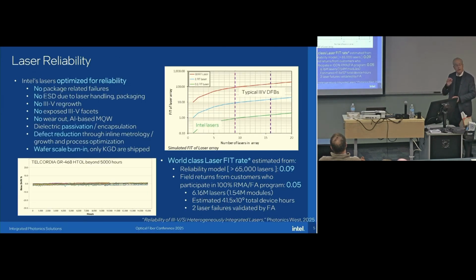But this is the real winner - I don't think any of us anticipated this at the beginning, but the reliability is phenomenally good. This is the reliability of a conventional, the best quantum well lasers Intel have procured over the years, now based on tens of thousands of lasers. If one laser fails, that's a 10 FIT - 10 failures in 10 to the 9th hours. The Intel lasers are down here, 100 times better than that.